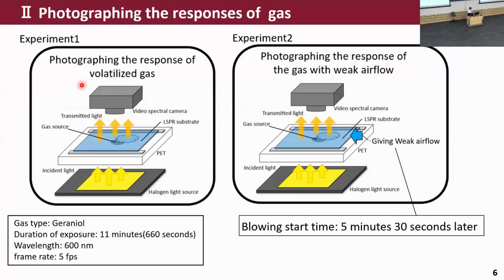We conducted 2 experiments. In the first experiment, we placed geraniol solution in the gas source and recorded the volatilization process for 11 minutes. In the second experiment, we recorded the volatilization process in the same way as in experiment 1. However, after 5 minutes and 30 seconds, we applied a weak airflow from the side.